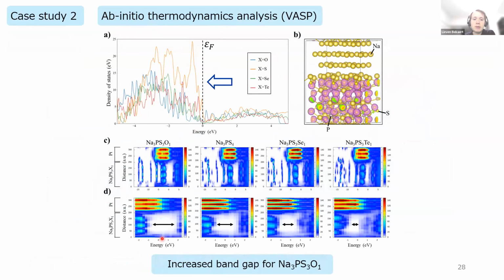And when you look at the band gap, you find that it increases towards using oxygen, which is also another beneficial property, which means that fewer electrons will be likely to enter into the solid state electrolyte. And this is a very good property for solid state electrolytes.